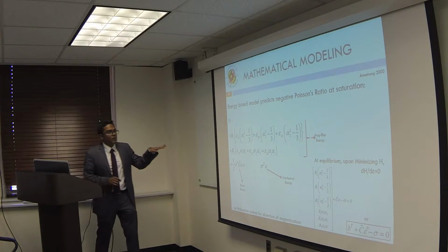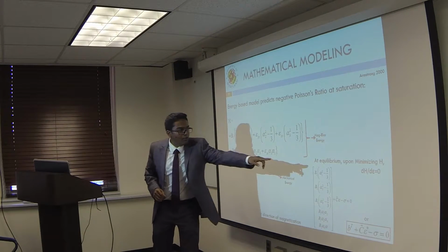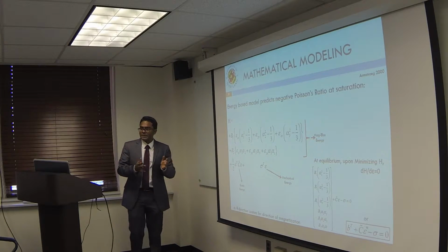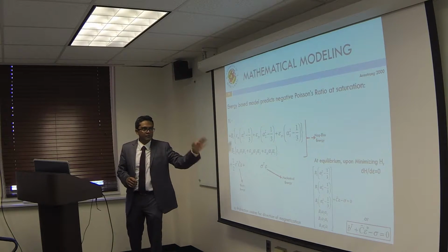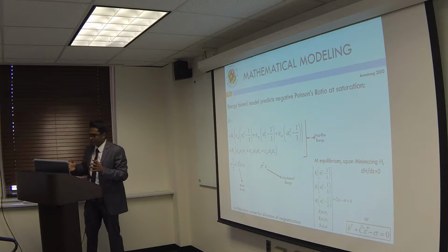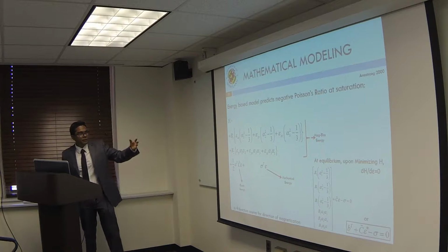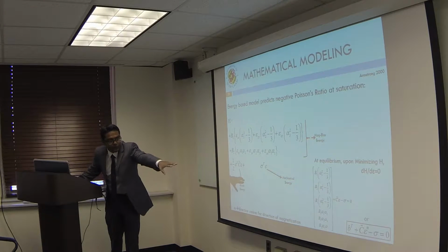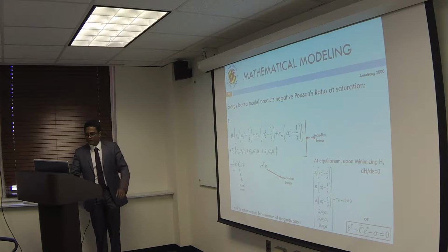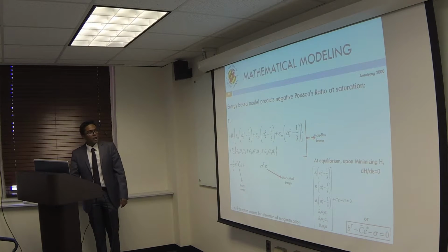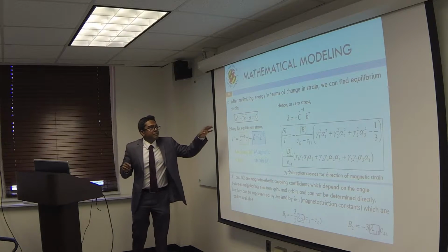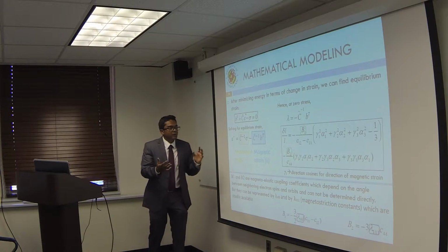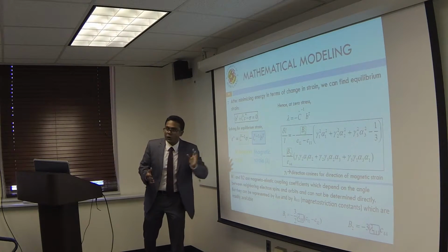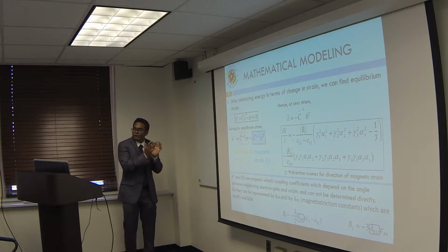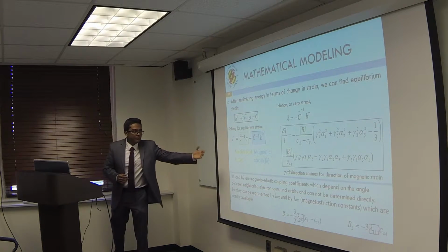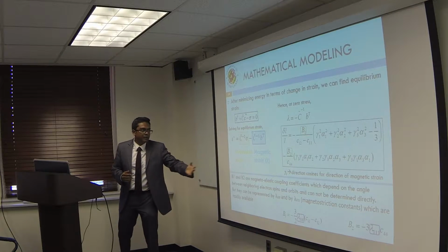So to determine the equilibrium strain, we have to differentiate with respect to the strain. So we get rid of all the terms which don't involve strains. And once I perform the differential, I'm left with that small equation on the right-hand side bottom of the slide. So after energy minimization, when I calculated the equilibrium strain, I find that there are two distinct quantities which add up to form the equilibrium strain.